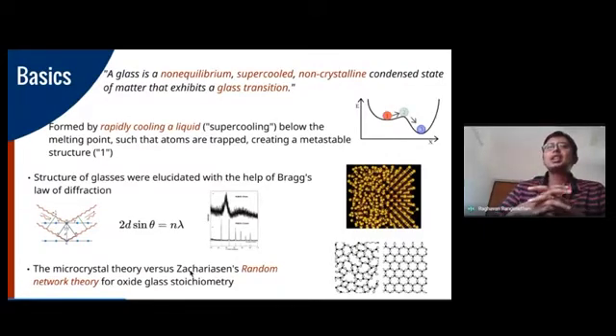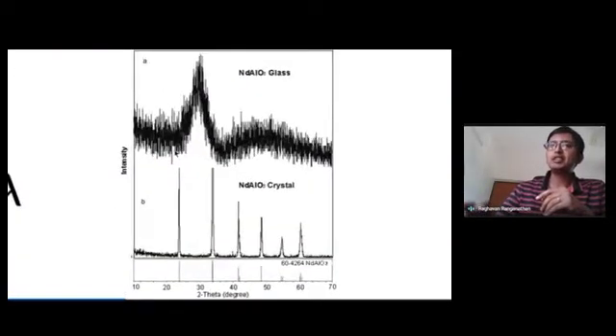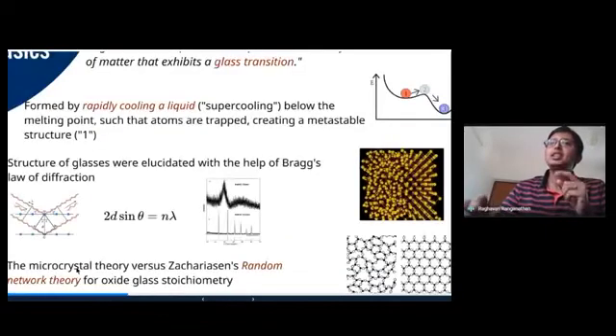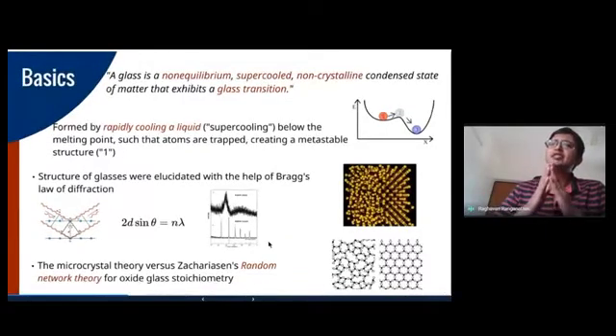What people thought was the glass structure was essentially something like a microcrystal, meaning all the glass crystals were very, very small, but they still had some crystalline order, meaning a periodic repetition of atoms. And it took a lot of time for people to look at the X-ray diffraction pattern and back calculate what the atomic spacing should be for this glass theory to hold. And this spacing that you see, the distance between the profiles of this peak, came out to be of the order of just one atomic plane, meaning the order in glass is actually very, very tiny.